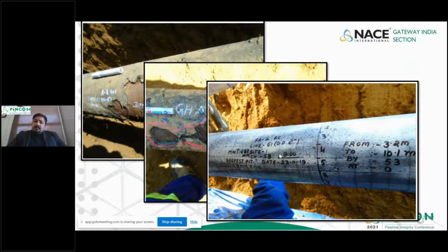If you see from the NACE perspective of the NACE ECDA standards, any of these above ground survey technologies are not supposed to be finding you external corrosion directly. They're supposed to be finding you indications. What is an indication? As per NACE, an indication is anything out of the norm, which is electromagnetic in nature, and is picked up by the above ground survey that was done earlier. But in this case, we are pretty lucky. We found holidays and we found associated external corrosion along with the holidays, and we could categorize them accordingly. So which is quite a successful process during this project.